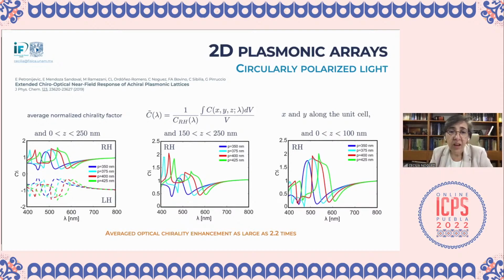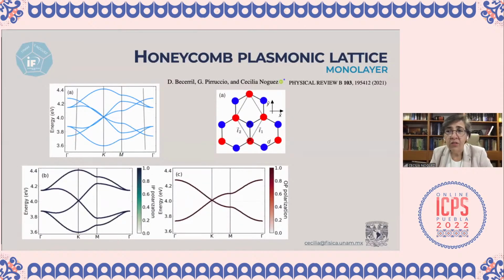Okay, I will just briefly look at this. Now we can make these hexagonal arrays, as I showed you. And if you look at the modes that you can find in these honeycomb plasmonic lattices, you can see that you have an analogue of graphene and these kinds of materials, with the linear dispersion of the plasmonic bands.